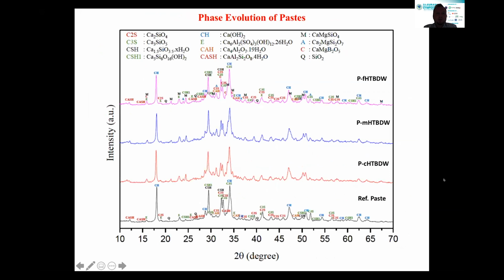So now you see the phase evolution of pastes. On the reference paste, we observed the known phases and also the major hydration products: calcium hydroxide, calcium silicate hydrate, and also a bit of ettringite phase. The heat-treated waste incorporated pastes have a similar XRD pattern, with just a bit of difference due to the phases coming from the heat-treated waste.